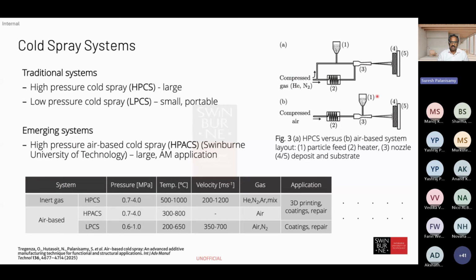So this is what I was trying to mention earlier. The compressed gas, you can see it goes in one direction, with helium and nitrogen for example, and it can heat the powder particles that come from the hopper and feed through the nozzle, which is a convergent divergent nozzle, which is able to propel the particles at higher temperature and high pressure also, as you can see here in this particular case.